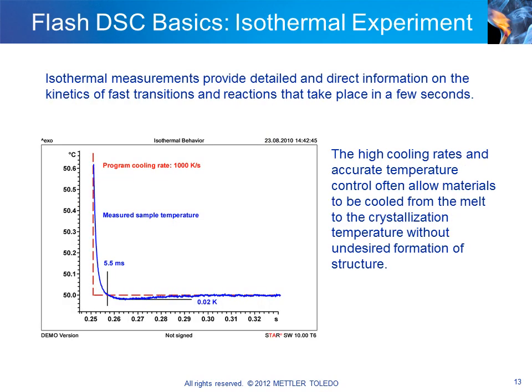It is often advantageous to use isothermal experiments to investigate the kinetics of processes involving structure formation. The sample is first cooled so rapidly from the melt to the crystallization temperature that no crystallization occurs. Following this, the heat flow is measured continuously during the isothermal crystallization process. Very fast chemical reactions can be investigated in much the same way.